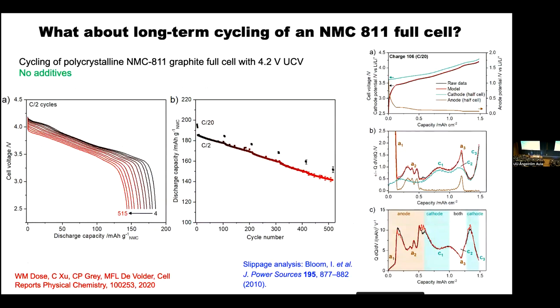So these are some really nice experiments done by Wes Dose, where he tried to unpick a lot of the degradation phenomena electrochemically. We started off, this is now 5 or 6 years ago, looking at NMC 811 graphite full cells with no additives so that we could then explore how the additives improved or stopped the degradation process. What Wes did was to use a slippage analysis where he was able to pull apart the processes that happened on the anode and the cathode by using the DVDQs, which unlike the DQDVs are additive.